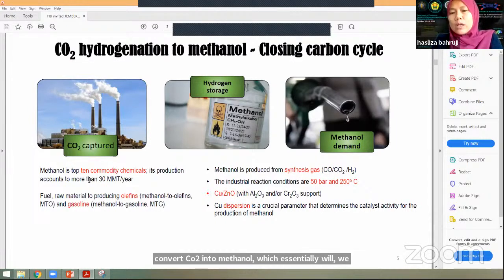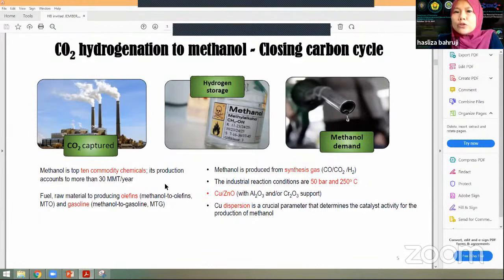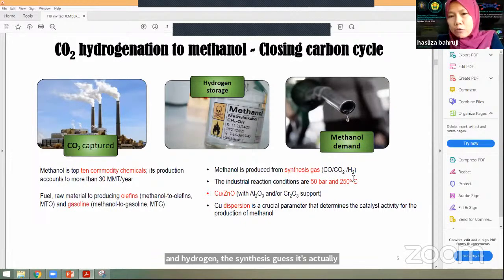We know that CO2 was produced based on the consumption of fuels to get to carbon dioxide. If we can convert CO2 back into fuel, basically we achieve a closed carbon cycle. Currently, methanol is a top 10 commodity chemical, and it is produced from a synthesis gas, which is a mixture of carbon monoxide, carbon dioxide and hydrogen. This synthesis gas is derived from natural gas through steam reforming, and the reaction normally requires copper zinc oxide, maybe on alumina or chromium oxide as a support.